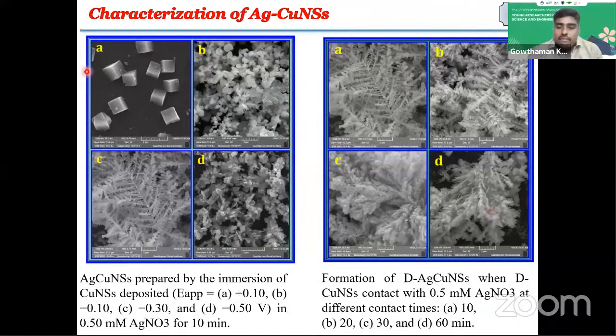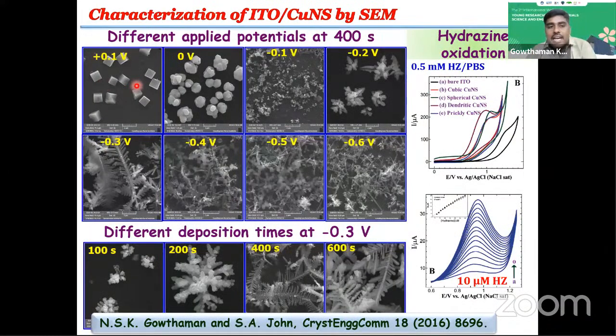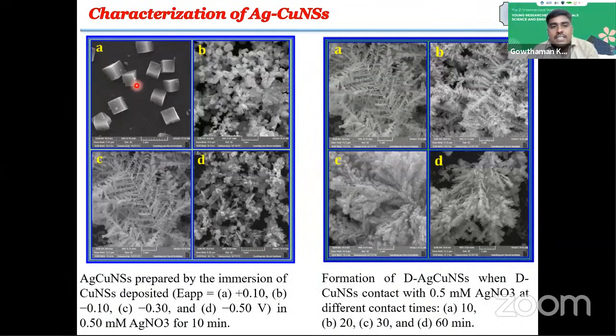See, when we take the copper nanostructure, there is a formation of silver over the copper. When you take the spherical copper, silver nanostructures cover the spherical copper nanostructures. Similarly, dendritic nanostructures are also formed. See that with different applied potentials, different nanostructures were obtained.